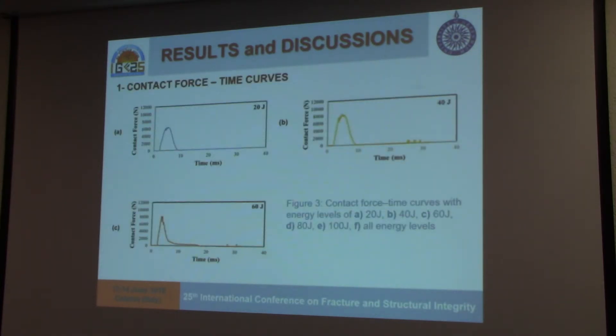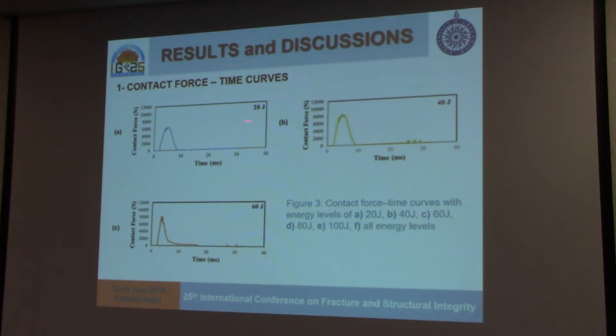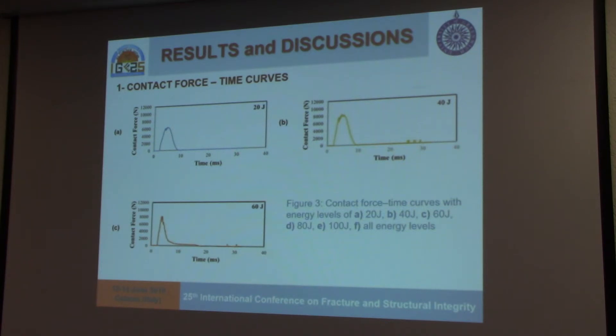After the experiments, to obtain the impact characteristics, we measured contact force versus time, contact force versus displacement, and contact force versus energy graphs. Starting with 20 joules, it is clear that as we increased the energy levels, the contact force was increasing slightly. For the first three energy levels, we have only one peak load, meaning the impact affected only the upper face sheet and the indenter was not going through the foam or the lower face sheet.